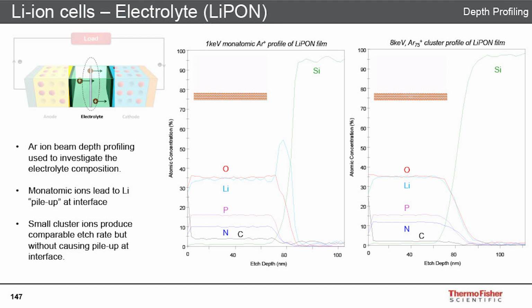And we thought, oh, that's interesting. I wonder why that's happening. And then we discovered that that was actually because of the monatomic argon beam. And so the ion beam was pushing the lithium through the sample as we were etching it. If we use the cluster source and profile it with quite an energetic cluster, so 8 keV and only 75 atoms, we're able to mill through the material quite easily, but we don't see that spike in the lithium concentration. And so we're actually measuring the film as it is.